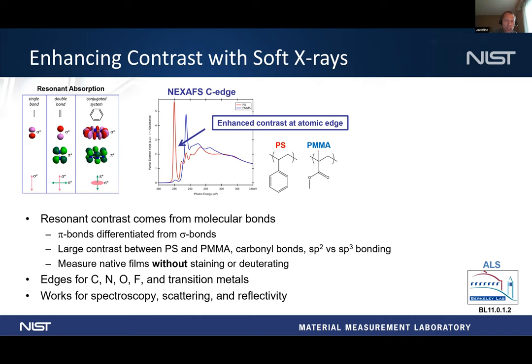And the nice thing with this is you can adjust the contrast between the different materials just by changing the energy that you're looking at. So you don't have to do anything with staining or deuterating to be able to get contrast, or to tune the contrast if you have more than two materials in there. And so we do this, obviously at the carbon edge, but we can also look at the nitrogen, oxygen, fluorine edges, and also some of the transition metals that are being used now for some of the new resists.